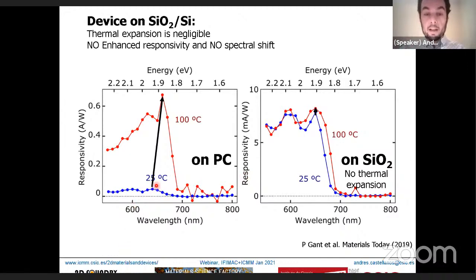Here I show an example of a polycarbonate device and a silicon oxide device. We ramp the temperature from 25 degrees to 100 degrees in both. You can see how in the polycarbonate device, the change in energy of this A exciton is much larger than on silicon oxide, and the enhancement of the photocurrent is also much higher for the polycarbonate device. So basically, the effect of thermal expansion and temperature change in all these features is very small.